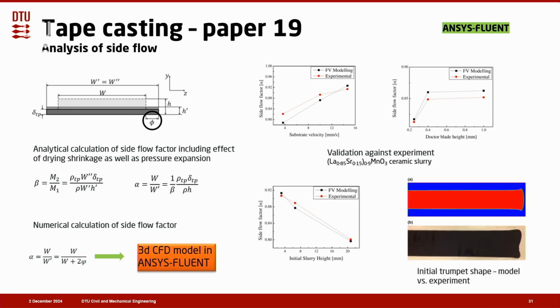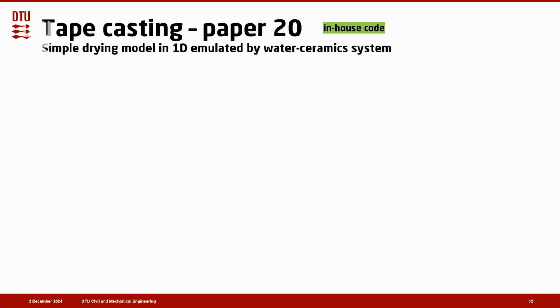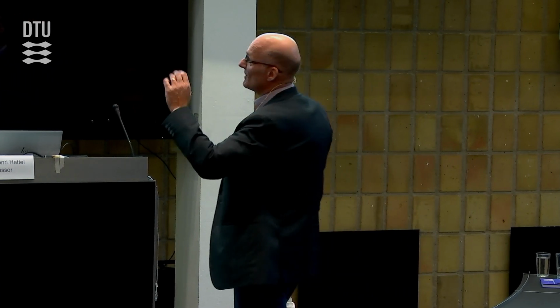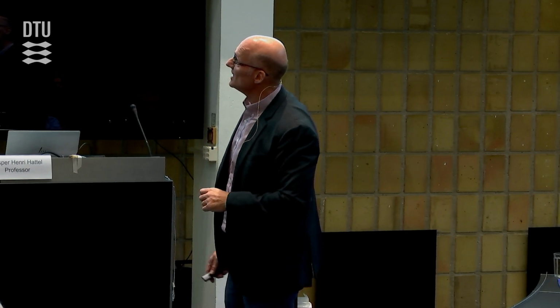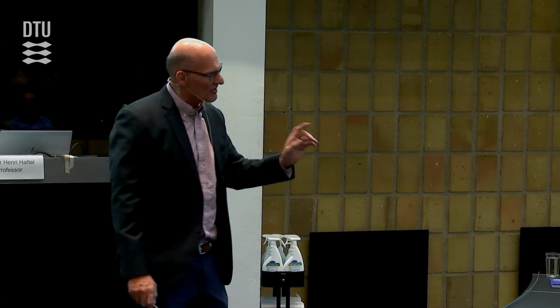And we could also predict the initial trumpet shape. We know how that looks. That's kind of a profile, right? But anyways, the initial trumpet shape, and that was the model versus experiment that you see here. And of course, it flows to the sides in the beginning very much because there is a free boundary very close. And then the final paper in tape casting was a simple drying model in 1D that was emulated by the water ceramic system.